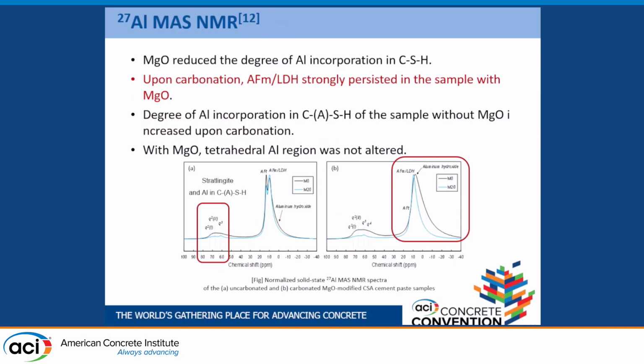This slide shows the NMR spectra of uncarbonated and carbonated samples. In the NMR spectra, we found that upon carbonation, AFm and LDH strongly persist in the samples with magnesium oxide. And as you can see, with magnesium oxide, which is the blue line, the tetrahedral aluminum region was not altered after carbonation.